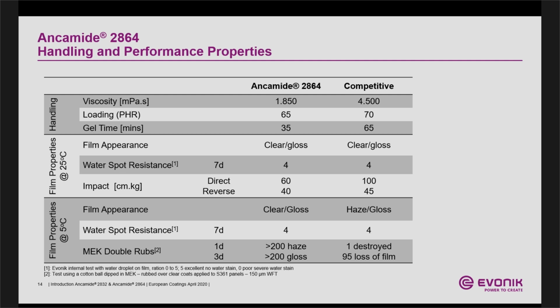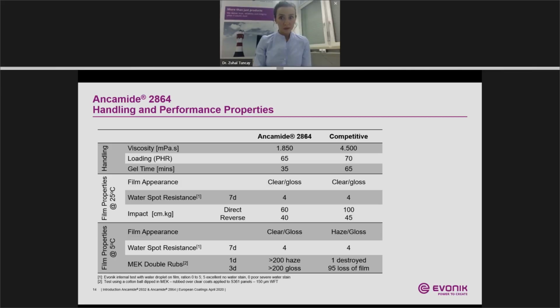After 1 day cure, when we apply an MEK swab on the coating, the film remains intact. But after 200 rubs, we lost gloss. After 3 day curing at 5 degrees, the coating provides more than 200 double rubs. And there is no loss of gloss and no damage on the surface to observe.